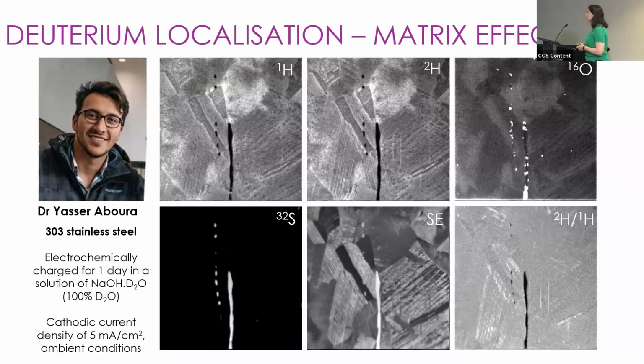Okay, so this is now a ratio of deuterium divided by hydrogen. And what you can see is that all that grain orientation structure has now disappeared. We're left with a flat background. And what it has really brought out, and what we're actually interested in now, is where the deuterium is localized. So it's showing us the relative enrichment of deuterium compared to hydrogen in this case. You can really see we've got a lot of deuterium enrichment in certain regions of our microstructure.